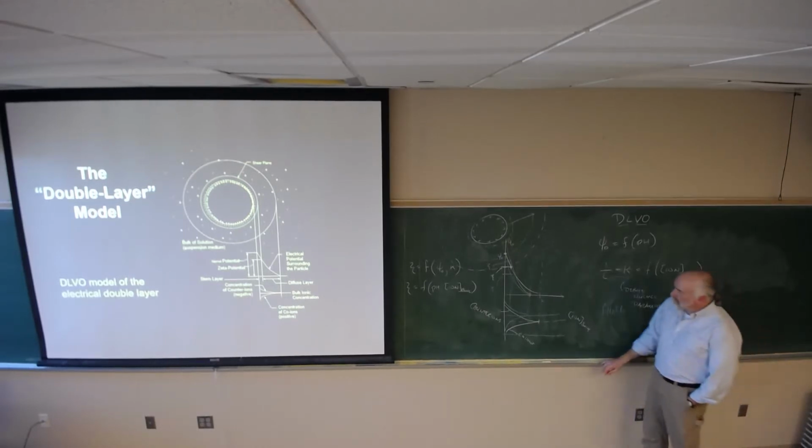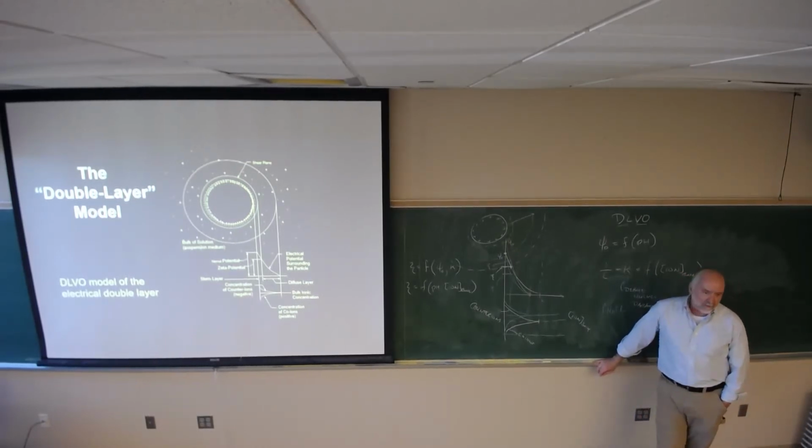All right, so what happens if I'm at the point of 0 charge? Okay, it's a straight line, but I still have a Stern layer. It's just that the potential at the Stern layer is 0, right? At the isoelectric point and the point of 0 charge, they are the same, assuming there's no specific affinity of anion or cation in the system, right?